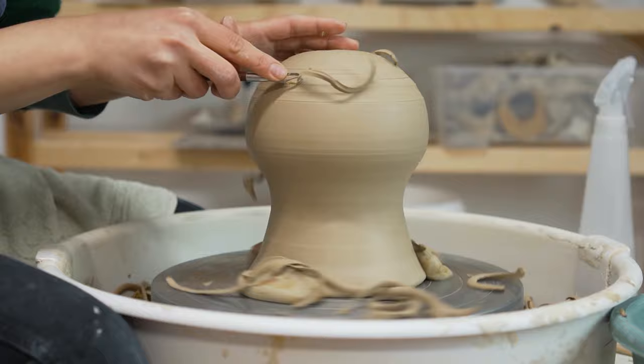I'm done. I think I'm seriously at risk of doing too much to these, so I'm going to call it here. I'm going to let these slow dry over the course of the next week. So first I'm going to wrap them up once again so all of the fresh clay can homogenize with the leather hard clay. I'll maybe leave it under plastic for 1 to 2 days, and then I'll unwrap it and slow dry it under some cloth.